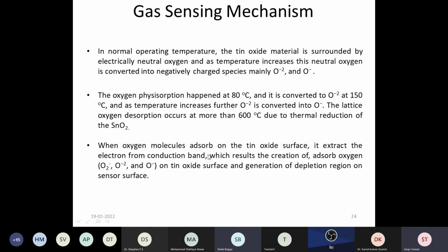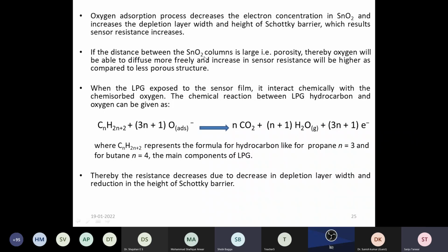The oxygen molecule adsorbed on the tin oxide surface extracts the electron from the conduction band, which results in the creation of adsorbed oxygen on the tin oxide surface and generation of the depletion region. As I explained, there is a variation in the Schottky barrier height. The oxygen adsorption process decreases the electron concentration, which results in the barrier height increasing.